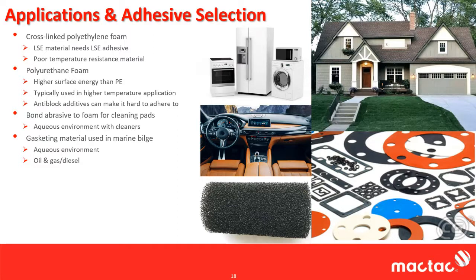So let's take a look at another aqueous environment, which would be gasketing material used in marine bilge or around the bilge pumps. So this is an aqueous environment. However, when you look at a lot of what you find in bilge areas of a boat, you find a lot of oil, you find a lot of gas, you find a lot of diesel fuels. These are things that are very detrimental to a rubber. So in these type of materials, cost isn't necessarily as important as, say, a disposable cleaning pad. And that's good because rubbers might not do well here because of all the organic materials floating around there. They're going to get in there, they're going to dissolve, they're going to plasticize the rubber, and it's going to break down. In this case, in this aqueous environment, we would use an acrylic adhesive.